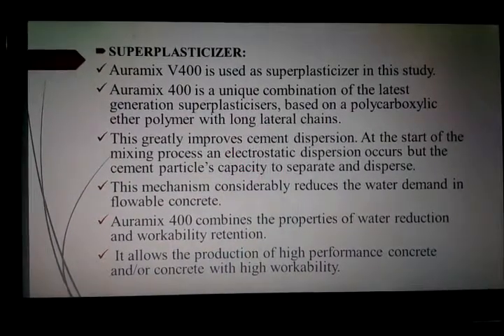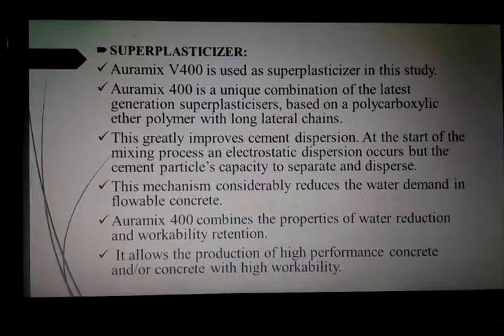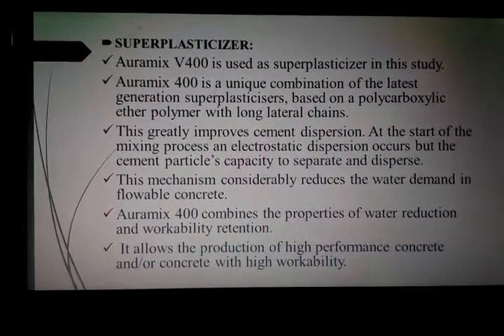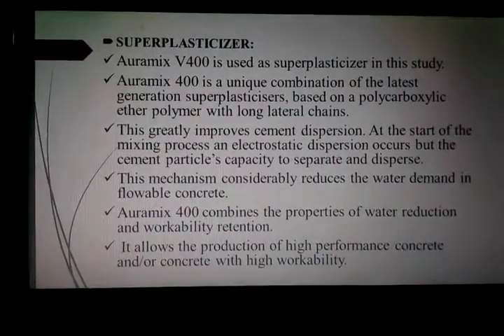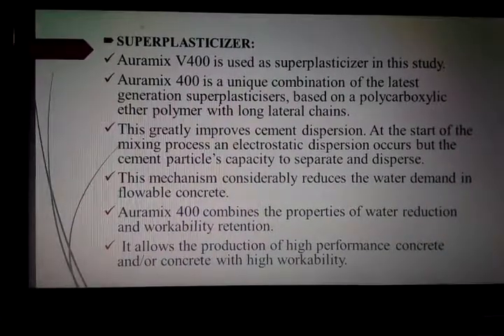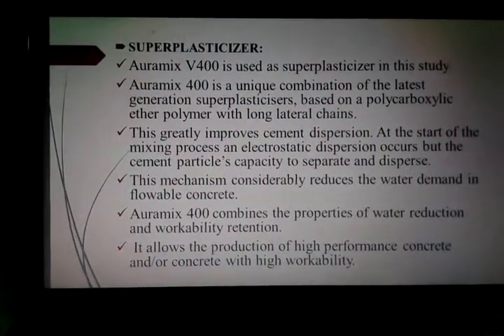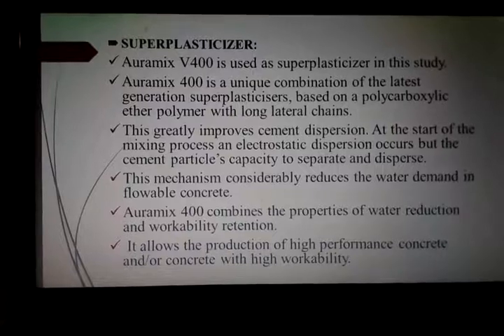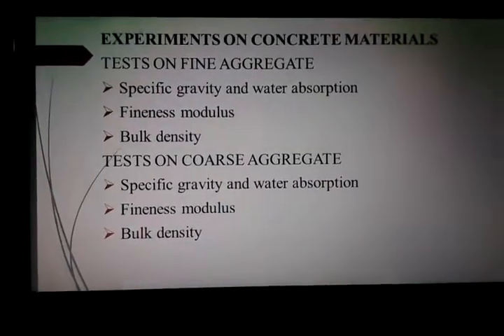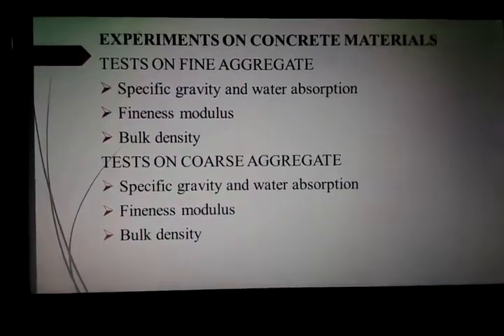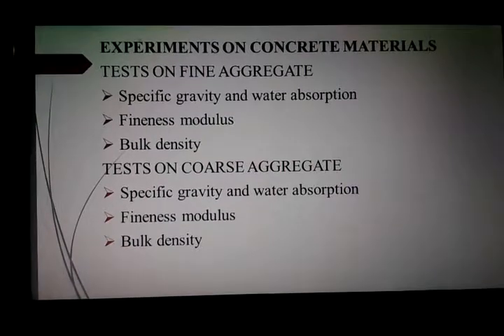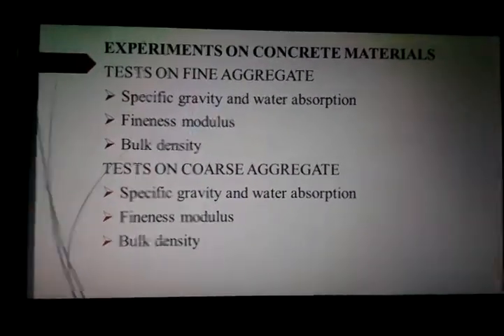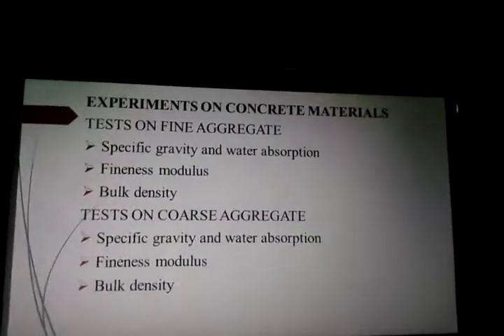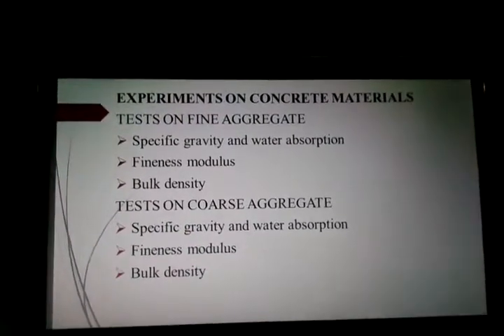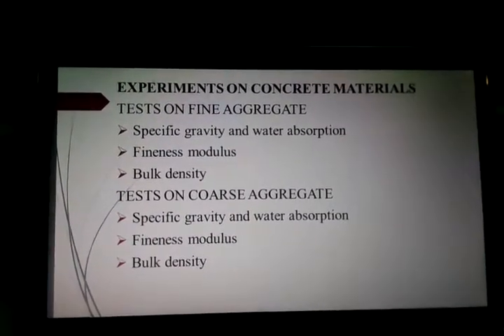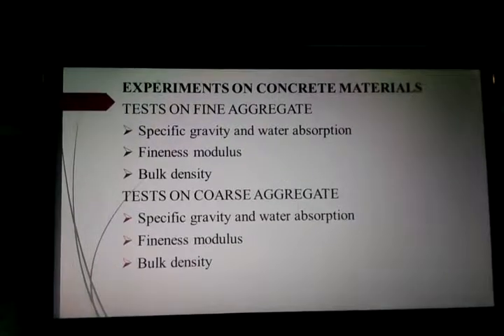increases. This mechanism considerably reduces the water demand in flowable concrete. Auramix 400 combines the properties of water reduction and workability retention. It allows the production of high-performance concrete with high workability at less water content. Experiments on concrete materials. Tests on fine aggregate are specific gravity, water absorption, bulk density and fineness modulus. The tests on coarse aggregate are specific gravity, water absorption, fineness modulus and bulk density.